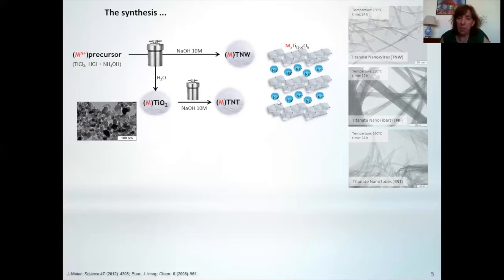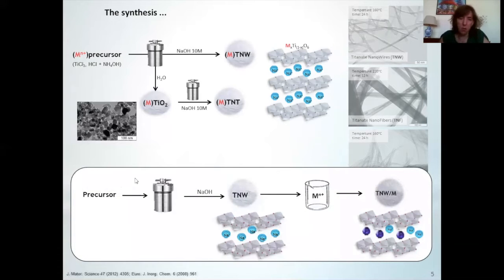But as I told you, we also have this sodium here in the interlayers. So why not try to replace it by, for instance, some metal? We just need to treat the nanowires or nanotubes in an aqueous solution containing the metal, and depending, of course, on the metal, because in this situation size matters, we will be able to introduce some metallic ions replacing the sodium.